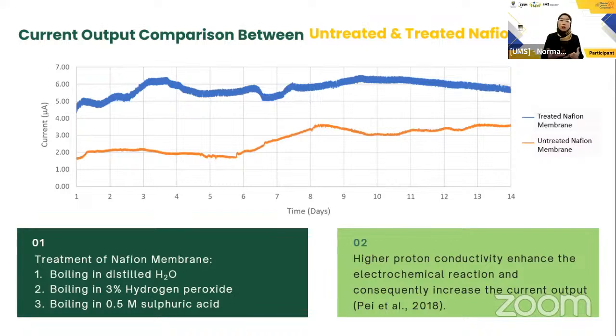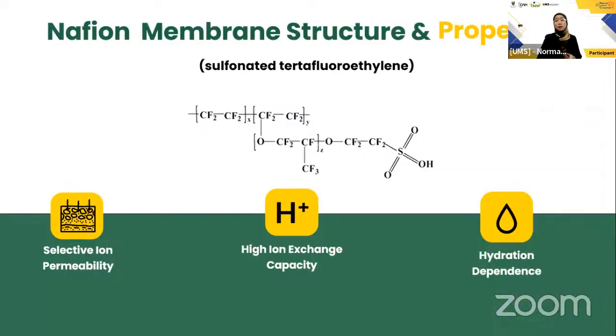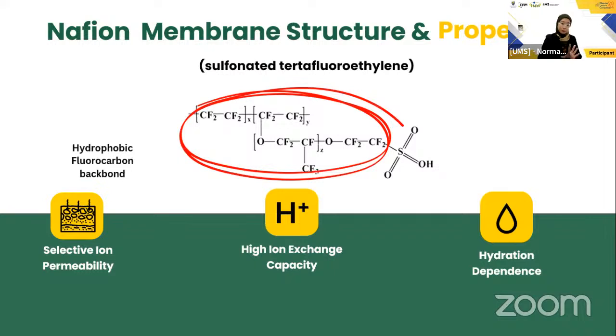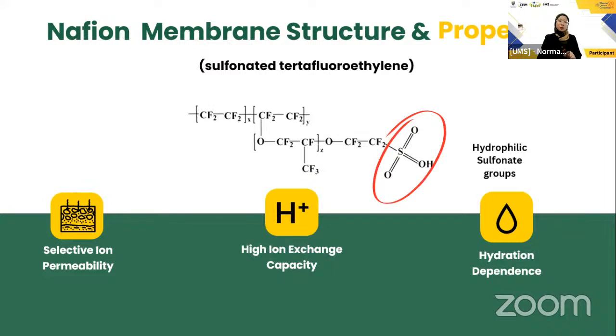So to understand further the factors that affect the efficiency of this proton transfer, we have to understand the properties and the proton transfer mechanism within this Nafion membrane. And to do that, we have to take a look at the structure. Nafion membrane is a sulfonated tetrafluoroethylene copolymer, which consists of a hydrophobic fluorocarbon backbone attached with hydrophilic sulfonate groups. This structure is responsible for determining the properties of this membrane. Due to the unique hydrophilic and hydrophobic structure, the membrane selectively permits certain ions such as protons, but blocks huge molecules and anionic species such as oxygen from passing through the membrane.